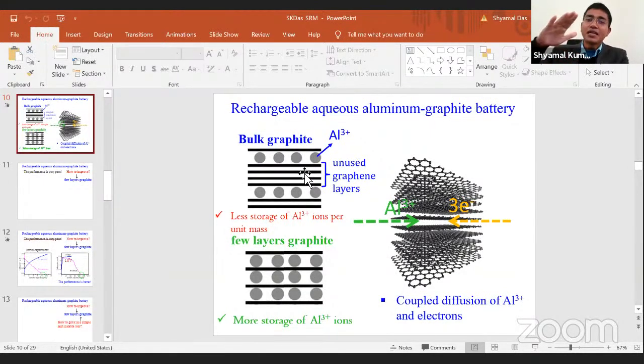But if you use only a few layers of graphene, let us say 5 layers or 10 layers, then we can very easily expand it because of ion intercalation. Because of that, more and more aluminum ions can go inside this structure. That is why we get more capacity when we use a few layers of graphene or a graphitic foam kind of structure.